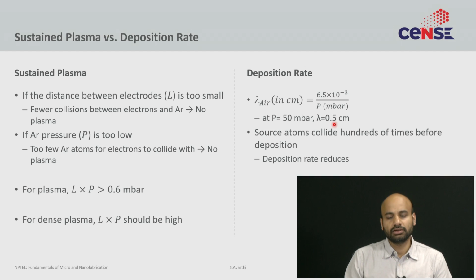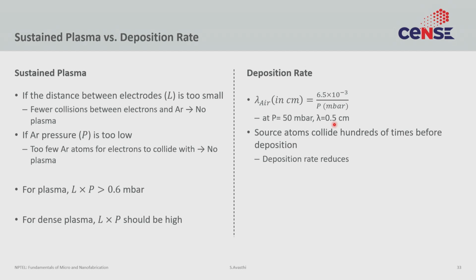Each collision can be a glancing ion collision, and just like in evaporation, each collision reduces the material usage and leads to lower deposition rate. Same in sputtering, each collision sort of reduces the probability of this neutral atom making its way to the substrate, and reduces the deposition rate. So for high deposition rate, you hence want this L to be as small as possible.